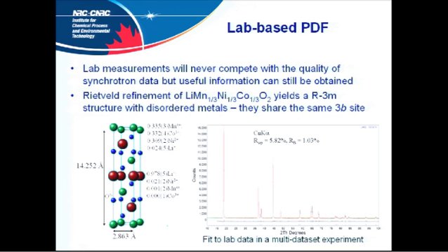Now, if you take this particular material just as a normal Rietveld fit, it was a multi-data set one, but this is the copper one. It actually fits really nicely. Disordered metals, bond distances are all nice and equal. But here you've got manganese 4, nickel 2, cobalt 3. Theoretically, the bond distances here are actually quite different, but here the disorder is such that they look the same.